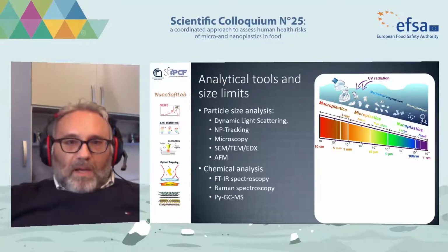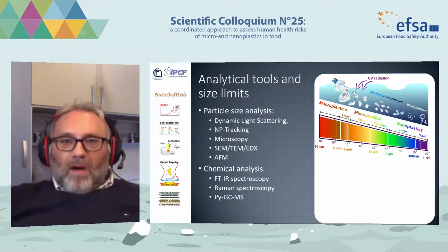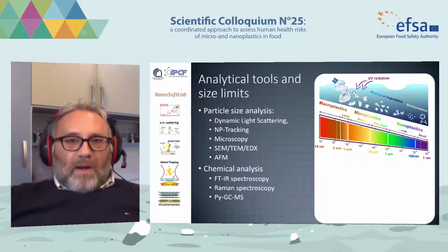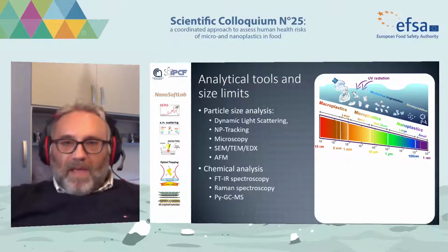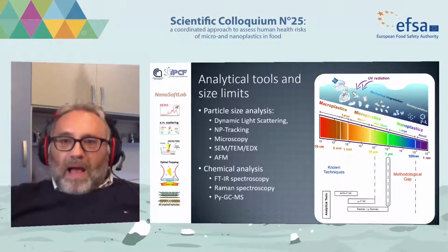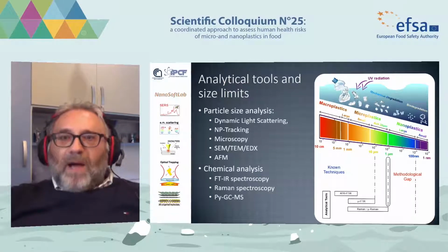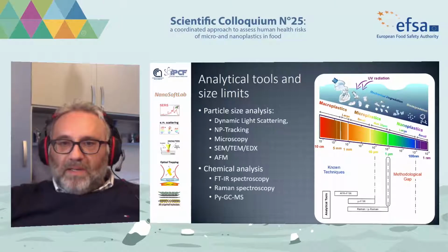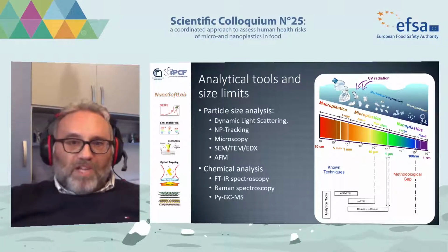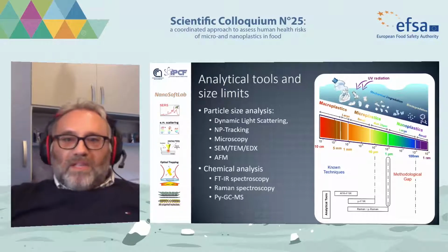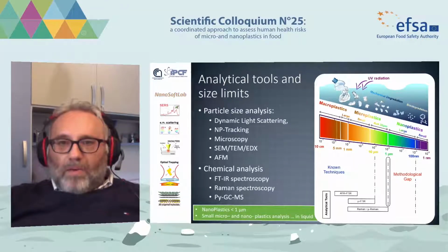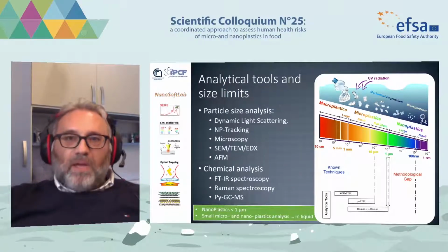The problem basically is when we deal with chemical analysis, so when we want to understand which material this particle is composed of. In this case, as we have seen, there are three techniques of election that are FTIR, Raman spectroscopy, and pyrolysis GCMS. The question is that when we come to the analysis of single particles, then we have basically a limit, as it has been shown, to the 10 microns or 20 microns regime for what concerns FTIR. For what concerns Raman spectroscopy, we can even go down to 1 micron or even to 100 nanometers. Actually, for some materials, we have very good sensitivity that permits us to go down to this size range.